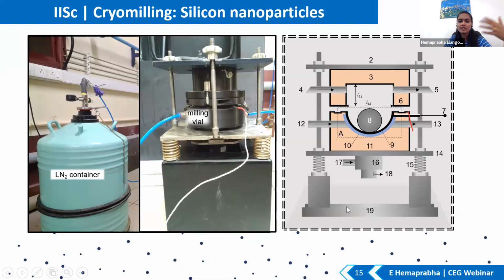If we need tons and tons of nanoparticles, and if we need to maintain 100 Kelvin, it's not easy to maintain that low a temperature. Then we need to supply lots of liquid nitrogen. Then again, it is huge consumption. So we have to give them a lot of parameters. And the first thing is, which temperature to maintain. At least we can do it in an indirect way. We can perform different experiments, one at 100, one at 150 Kelvin, one at 200, one at room temperature, so that we can compare the results and then give the answer.